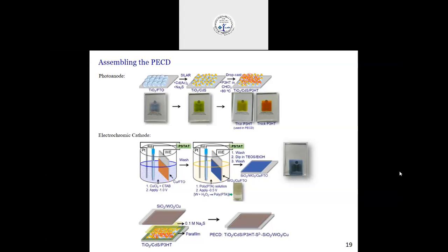Actually, we have used commercial FTO, so I'm not clear about the question, whether the transmittance will hamper or not. Whatever commercial FTO we have used, before coating the material, we have gone for delta T transmittance measurement, and we have got it close to 95 to 100%. And if we have not, then we'll set the baseline to that level, so that when we do the measurement, the transmittance of FTO is not hampered with the film. Am I clear, sir?